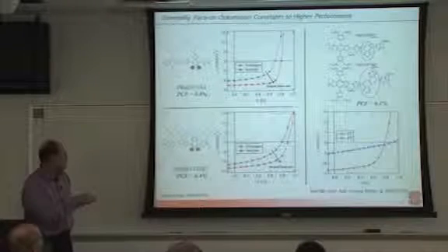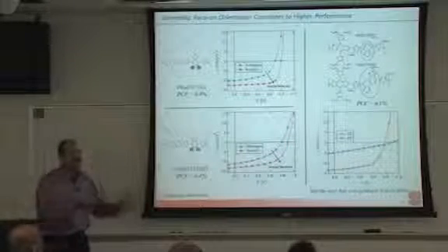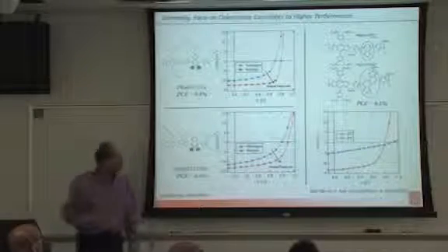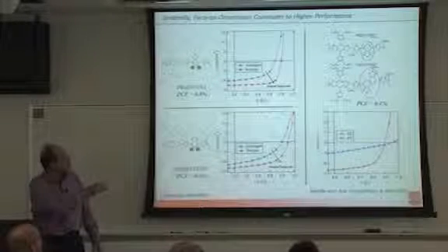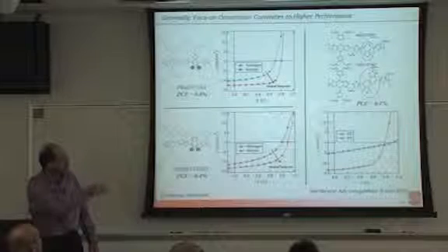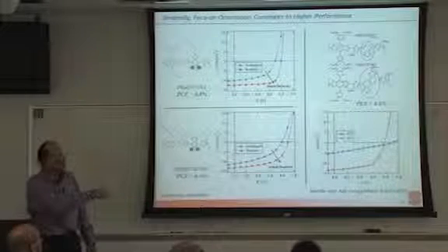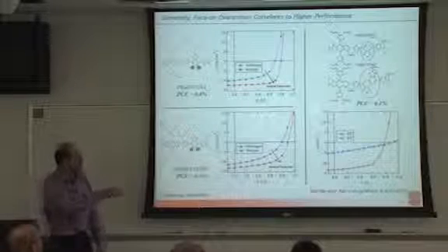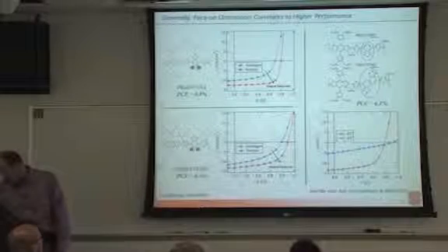Here too, as I fluorinate, I again change the performance, and every time I get more face-on orientation. This is another system where the backbone changed and drastic difference. The high performance is again face-on relative to the interface. In this case though, the domain size and purity also changed a lot, so one couldn't really draw conclusions.